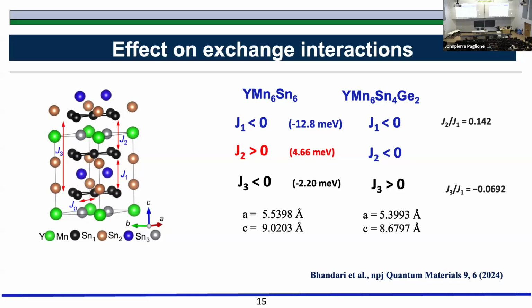The ratio, this is the experimentally determined ratio. From the angle, you can calculate these ratios of the J. Just calculating the J is difficult this way. And once you calculate that, then you see that the sign of this one is reversed, and this one is also reversed. And because of that, we see these changes. It's all about playing with the exchange interactions that drive the magnetism in the system.